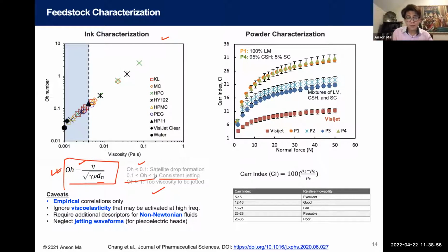This is done empirically, and so that's a good check, right? Back then we looked at a series of different inks with different concentrations and different polymers incorporated, and then you can do this calculation and map out essentially what would be the workable zone for your material. And then you can take that ink and put it in a print head and do more careful calibration